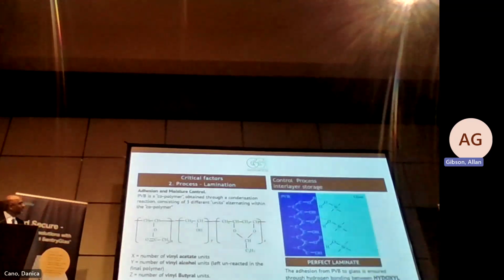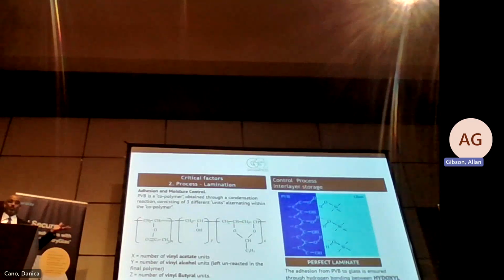Just a process. This is the lamination process. It looks easy: loading, cleaning, drying, positioning, roll storage. It looks like a laundry thing, but it is not. De-airing process, unloading, and then the autoclave process. Next. We have spoken about this. At least for PVB, it is the hydroxyl groups from the PVB which are bonding to the glass, and that's the perfect laminate that you would have. But unfortunately, there is no laminator who can give you this sort of a perfect laminate. Next slide, we will look at it.